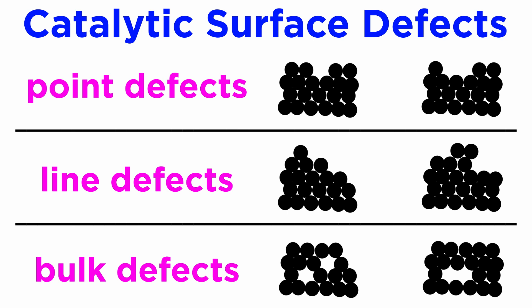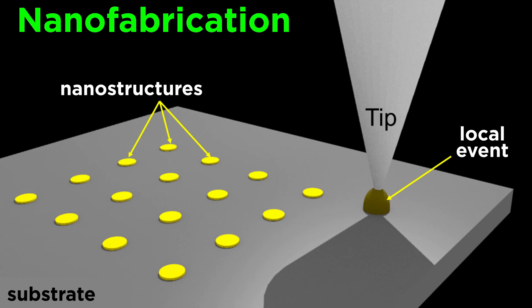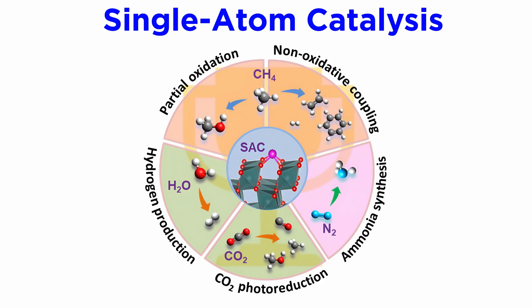The analysis of lattice defects in catalysis is actually a fertile research area in itself. Here we can see a few of the typical defects found in catalytic surfaces: point defects, line defects, and bulk defects, which describe different ways that the crystal structure can be altered. These and other types of defects result in variability for the catalytic performance of solid catalysts. Modern nanofabrication techniques are resulting in the formation of much improved surfaces with more precise control at the single atom level. Single atom catalysis is touted as a brand new exciting field, which in the near future may provide us with much improved heterogeneous catalysts.